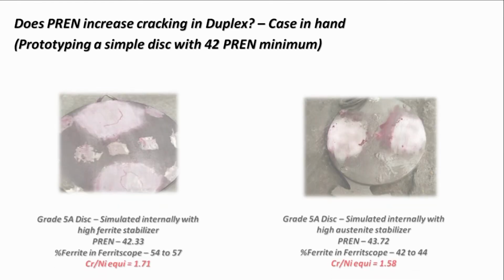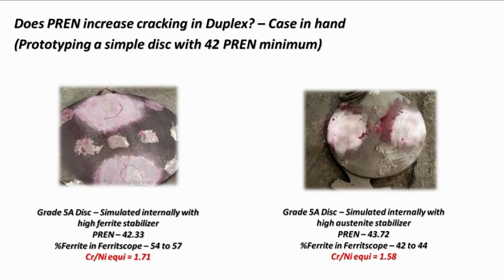So to understand it better, we did some prototyping of a simple disc in our foundry. You can see the left side is a grade 5A disc made with PREN number 42.33, and the material has a crack under the riser where the ferrite is around 54 to 57%. On the right you can see the disc made of 5A with PREN number 43.72, but the ferrite we achieved is 42 to 44%. So it is better, and it is up to us to control the ferrite by monitoring the chemistry of the material.